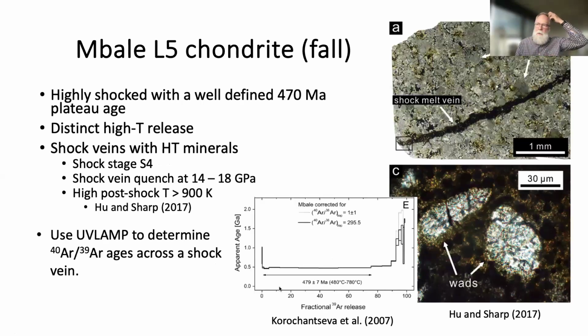And so we actually looked at Mbale. Again, I'll come back to this L5, L6 chondrite. It's highly shocked. We studied it a little bit earlier. It has a distinct high temperature release, as we see from the data we just showed, as well as this late release. We know the shock veins have high pressure minerals. We just sort of showed that. So at ASU, what we did is we used their laser system in Hodges' lab, and this is a UV laser. So the technique is called UV laser ablation microprobe.